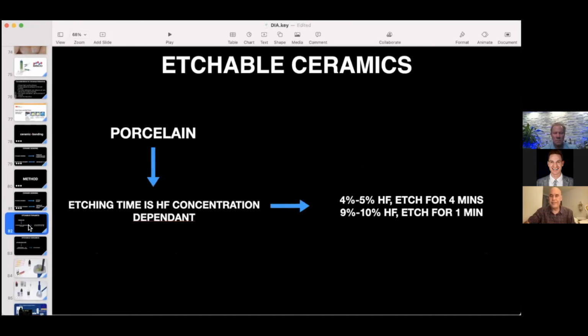Now, feldspathic porcelain. Do a lot of people use feldspathic? You have a group of people that do feldspathic porcelain, specifically veneers. When it comes down to etching feldspathic porcelain, your hydrofluoric acid concentration will have an effect on the etching time. So I'm going to tell you guys, there are 2 types of hydrofluoric acid. You have your hydrofluoric acid, I don't like to call it low concentration, but I'm going to say it is between 4 and 5%. And then you have hydrofluoric acid that is between 9 to 10%.